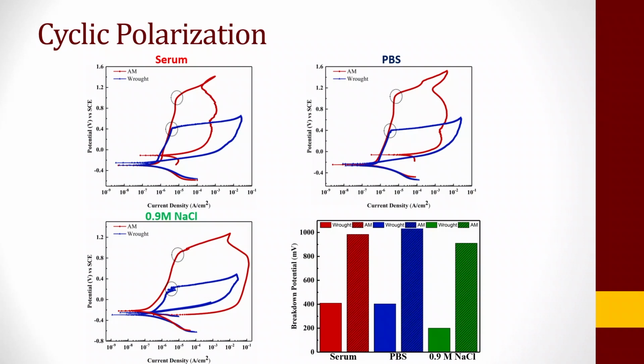And now these little circles are representing the breakdown potentials, so the breakdown potential for additively manufactured samples in all the 3 mediums is much, much higher as compared to the wrought counterparts. And again, this histogram is showing exactly the same thing.